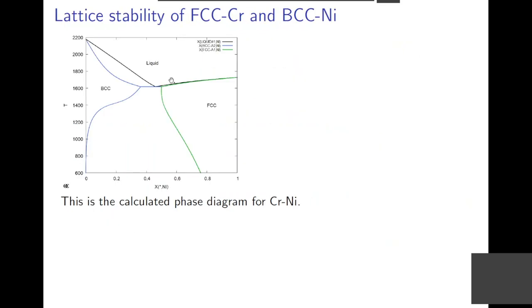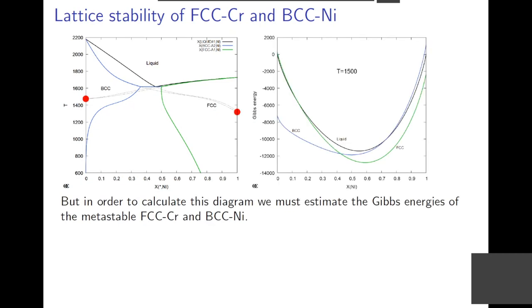To understand the lattice stability, one can take a phase diagram like this simple one for chromium-nickel. You have pure chromium here, which is BCC at all temperatures up to the melting. And you have nickel on this side, which is FCC up to the melting temperature. But in order to calculate this equilibrium between the liquid and the BCC or FCC, and also in the solid state, you need to predict properties of pure chromium as FCC. And you can never measure it. You have to establish the value for that one.